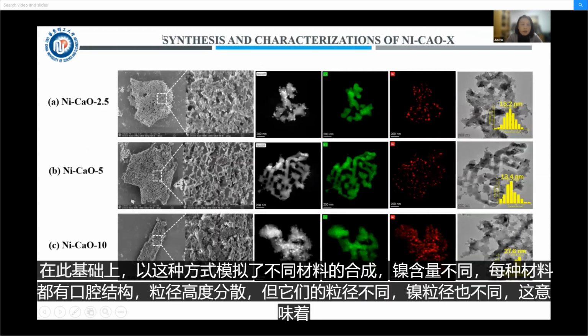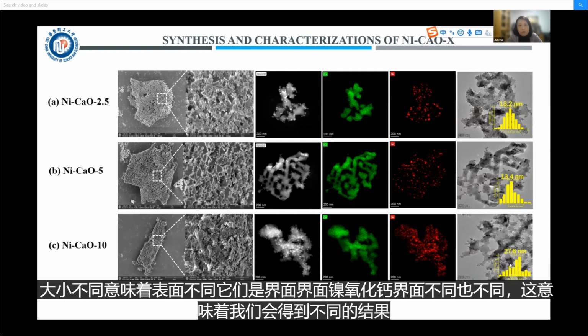And guided by this, we synthesized different materials with different nickel loadings, and each one has a porous structure and highly dispersed particles, but they have different nickel particle sizes. That means different surface areas, and the nickel calcium oxide interfaces are different, and that means we will have different results.